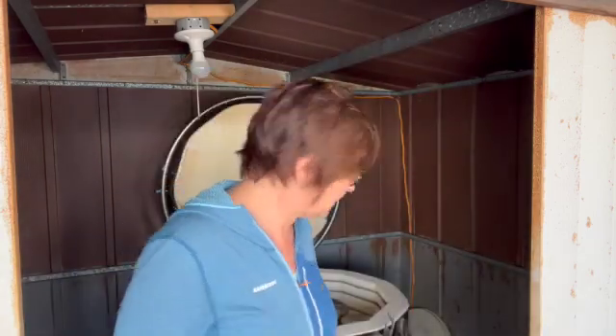So, a kiln unload for you to show. I've already had a peek, maybe a few little redos in there. And this kiln was a slow cool schedule with a top temp of 2190 and a slow cool down to 1900 and held for 30 minutes and then cooling naturally after that. So let's just get started.